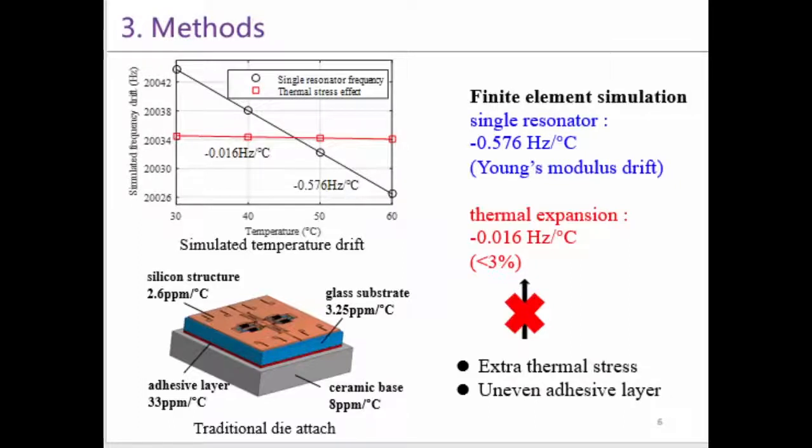The simulation results show that the drift of a single resonator is negative 0.576 Hz per degree Celsius, which is mostly due to the Young's modulus drift. And the frequency drift caused by the thermal expansion is negative 0.016 Hz per degree Celsius.